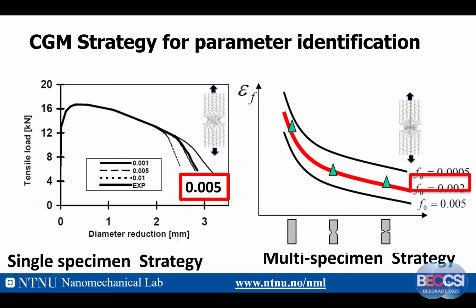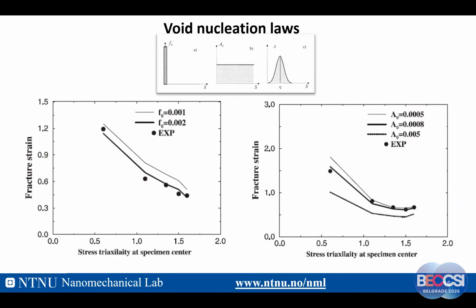Then one fits the experiment very well. If we use the multi-specimen strategy, then we can fit the ductility. We can also use different integration models. If the cluster model is not working, then we can use the continuous model. And if the continuous model is not working, then we can use the statistical model. So my advice is to try the simple model first.